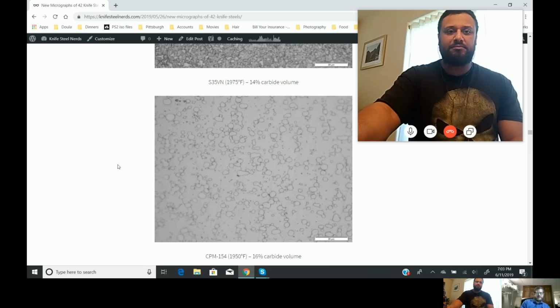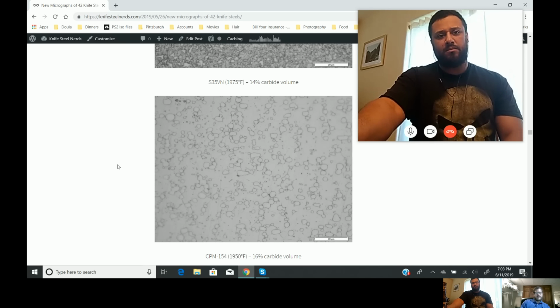But one thing we might discuss a little more is just carbide structure does not control everything. So there are steels with a really small amount of really tiny carbides, and they are not that tough. So 1095, O1, really small carbides, not that much carbide, but they did not test that well on toughness.